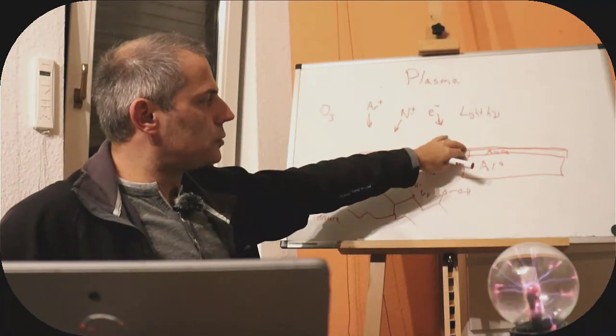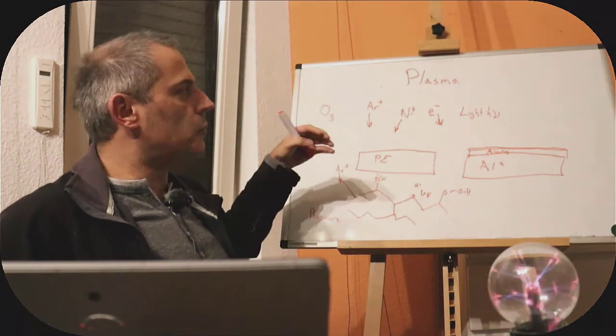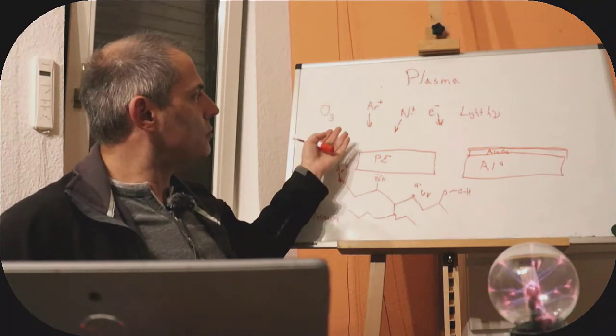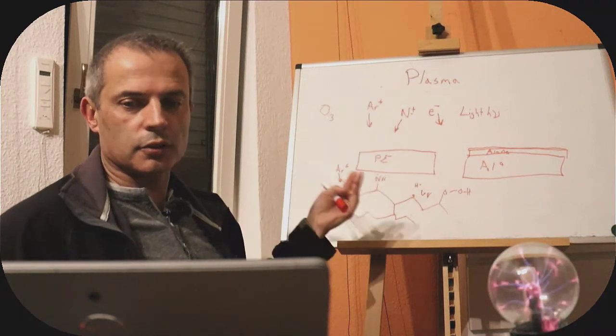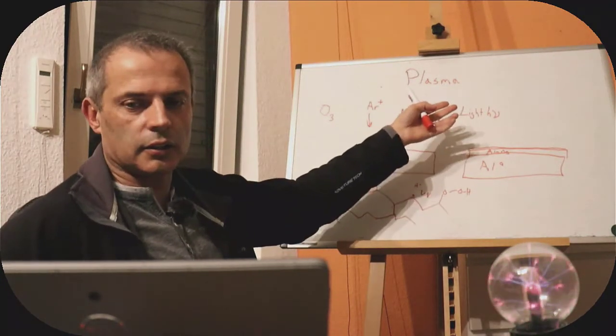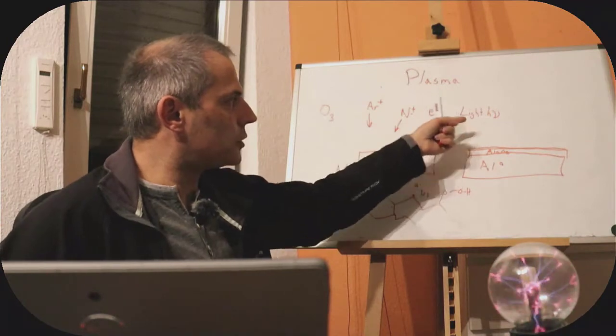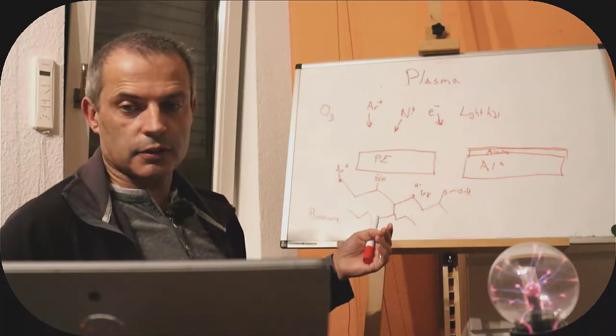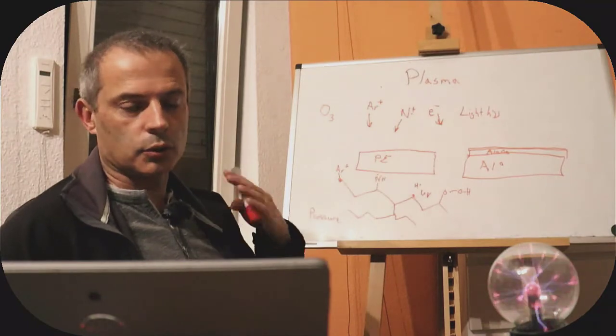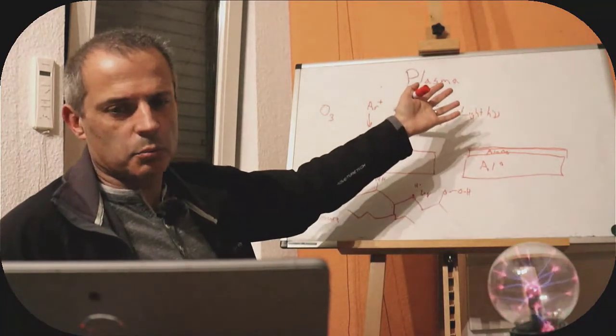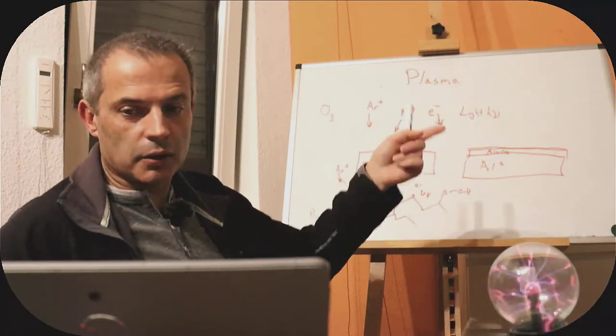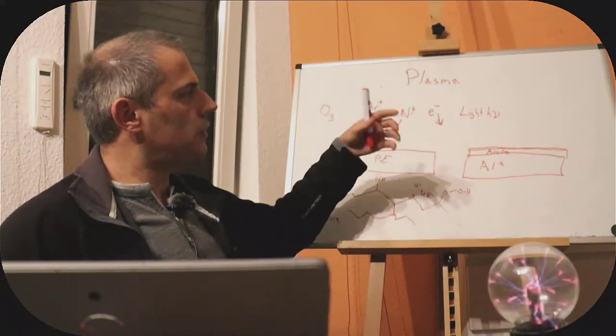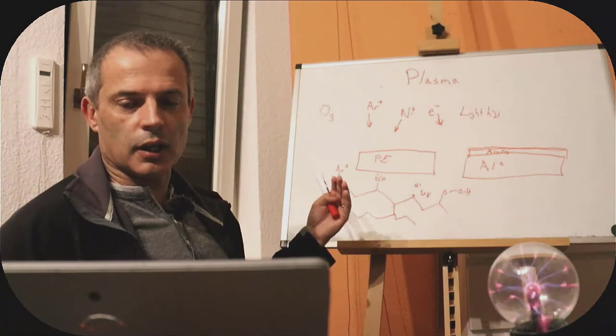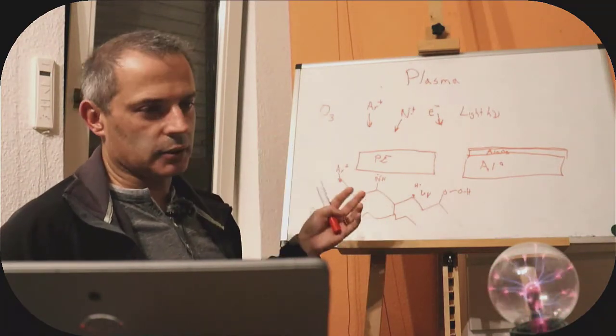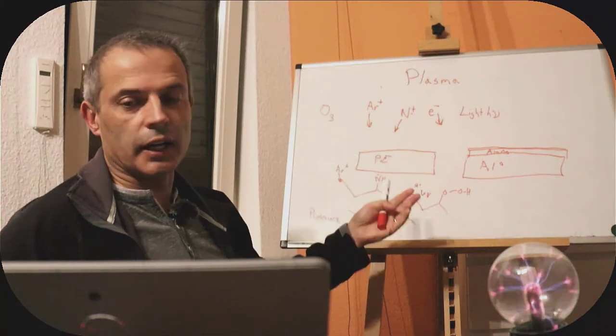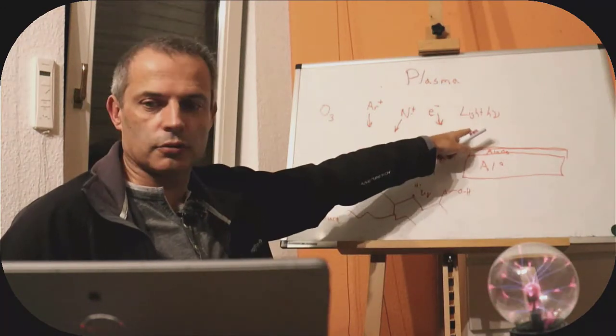If we want to treat with ozone, then we can use a higher pressure, and that will tend to remove some of the other species, so we won't get so many ions floating around. We will get light and ultraviolet, so typically we will have ozone and ultraviolet, and they will affect our surface. We can put a baffle in the way, so we can have a piece of metal in the way, paint it black even, and the ozone can just go around it. Light can't go around corners, so we get different physical ways of separating them. Likewise, if we have a quartz bulb, we can have just the ultraviolet.